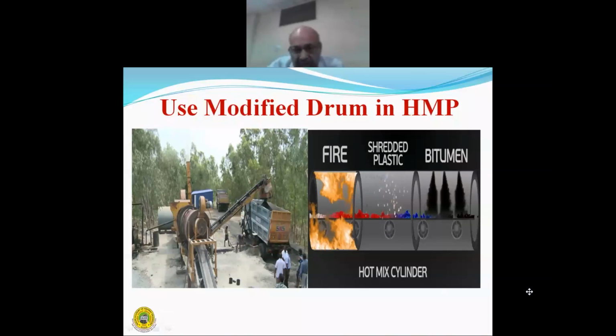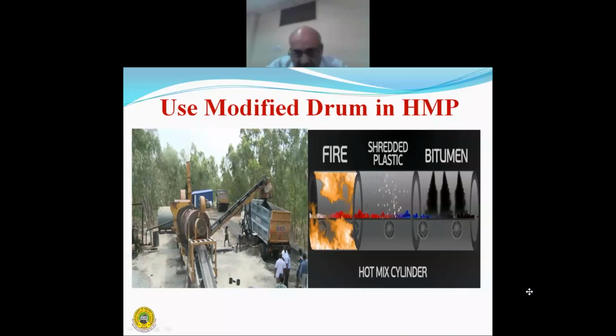Plastic before shredding may be packed like this, as shown in the picture, in net, and this is storage and handling to be packed after shredding. It shall be packed into these bags. Specification: the plastic waste shall be consistently polypropylene, and plastic waste shall be shredded to the size of 1.75 mm.